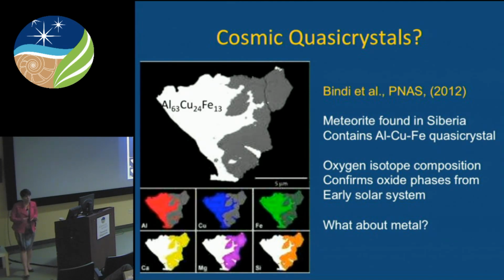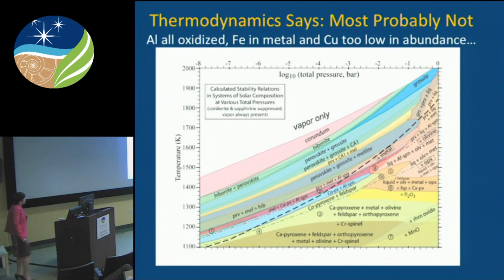Although the oxygen isotope measurements show that these phases out here, which are spinel and other components associated with calcium aluminum rich inclusions, have an oxygen isotope signature indicative of formation in the early solar system, so the meteoritic looking component of oxides really is meteoritic, the quasi-crystal metal itself really doesn't belong there thermodynamically, and you can go back to the phase diagram and see